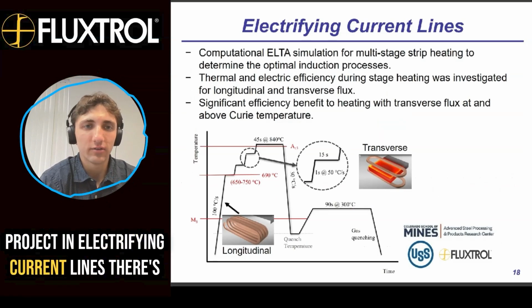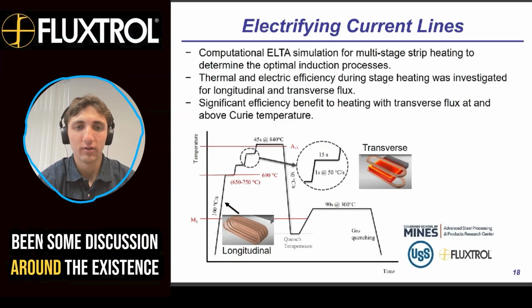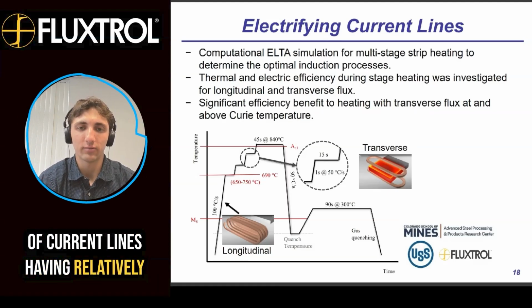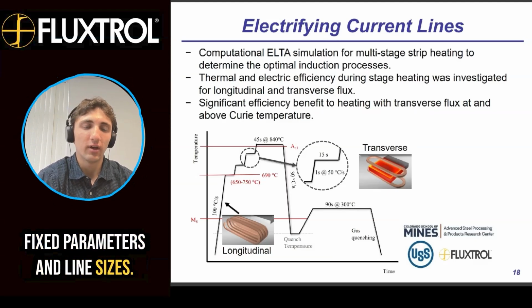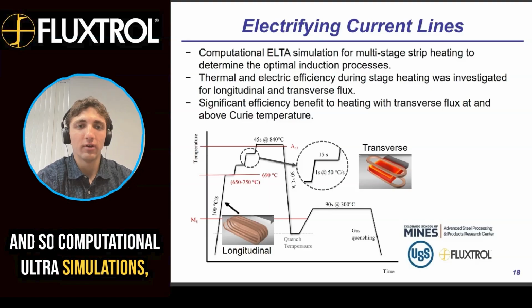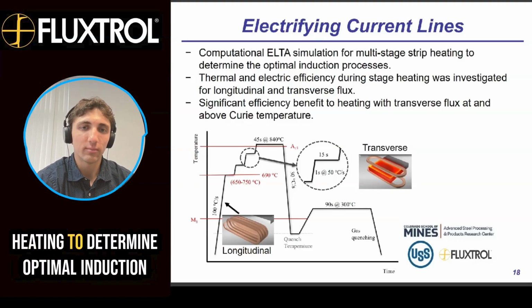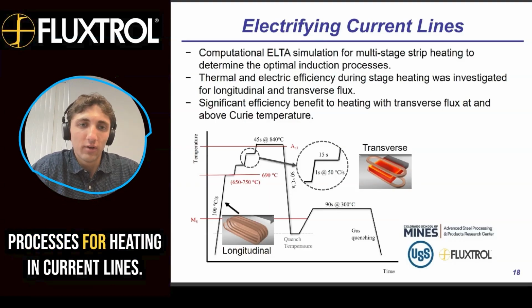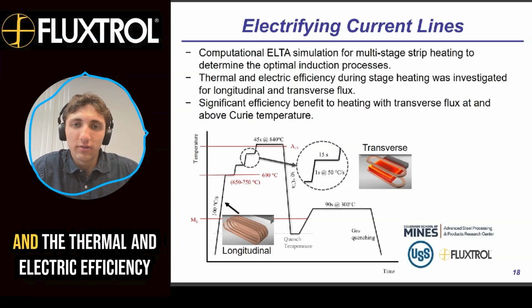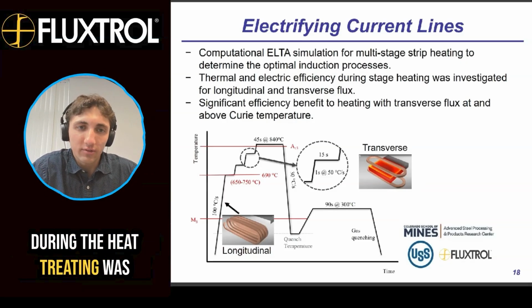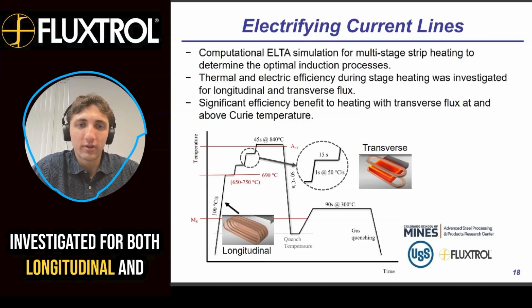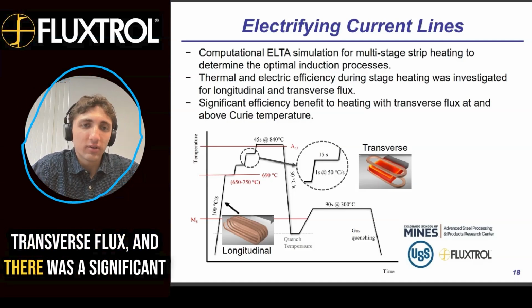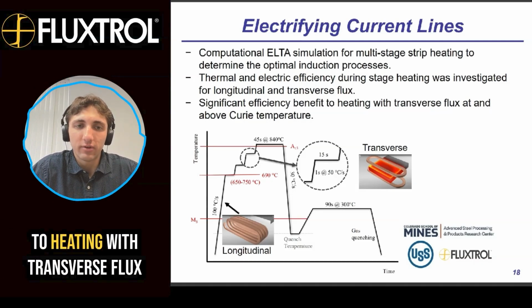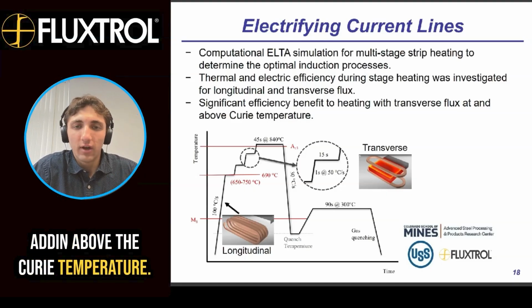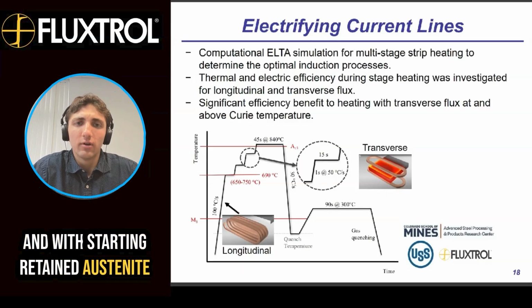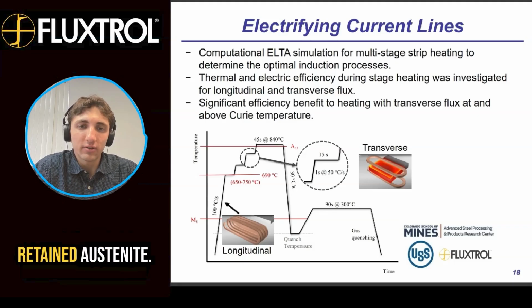In electrifying current lines, there's been some discussion around the existence of current lines having relatively fixed parameters and line sizes, and so computational ELTA simulations were conducted for multi-stage strip heating to determine optimal induction processes for heating in current lines, and the thermal and electric efficiency during the stage heating was investigated for both longitudinal and transverse flux. And there was a significant efficiency benefit to heating with transverse flux at and above the Curie temperature, and with structures that had starting retained austenite.